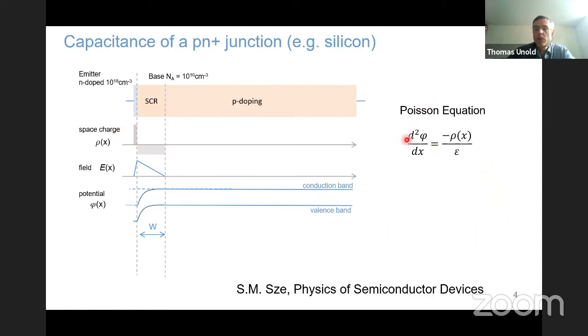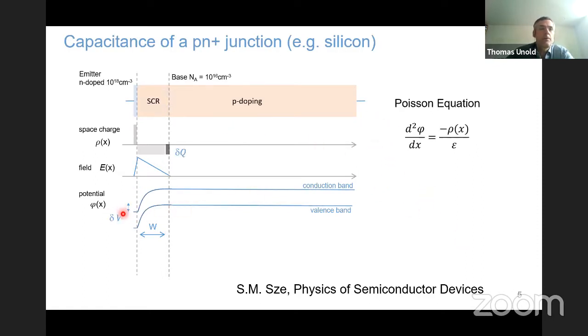And then you basically only need the Poisson equation that was already mentioned, and you can calculate the electric field here in the space charge region, the band bending, so you can construct your band diagram and so on. And now if you do a capacitance measurement, what you do is you apply a little bit of a voltage. So you increase the voltage a little bit from one side to the other side. What happens then is your space charge width widens, you get this extra space charge here.